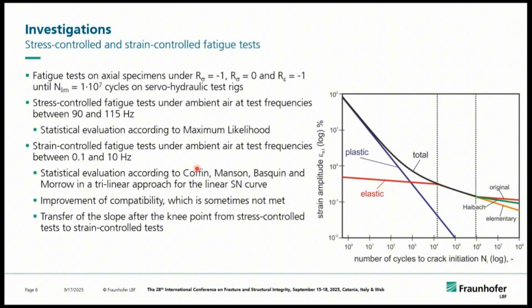We made the evaluation basically on Coffin-Manson and Basquin and Morrow, but with a trilinear approach. I don't want to go too much into detail in this approach, but we see that sometimes this trilinear approach improves the compatibility between the strain life and the stress life curve. At the end, what do we do in this approach? We separate the elastic